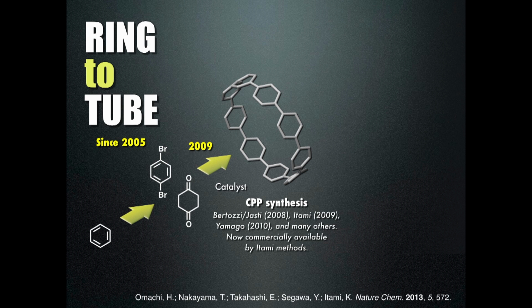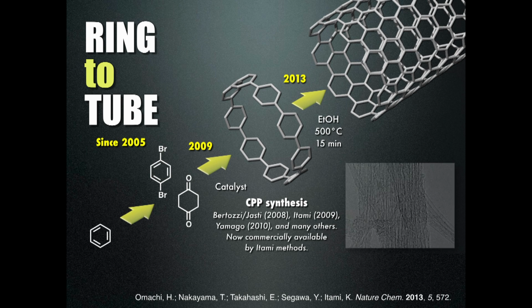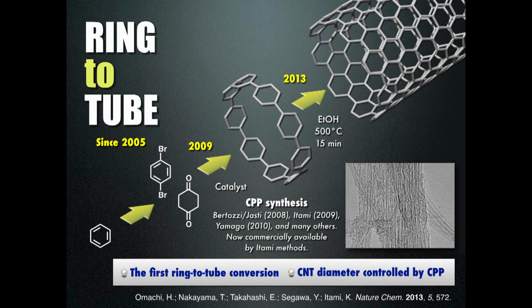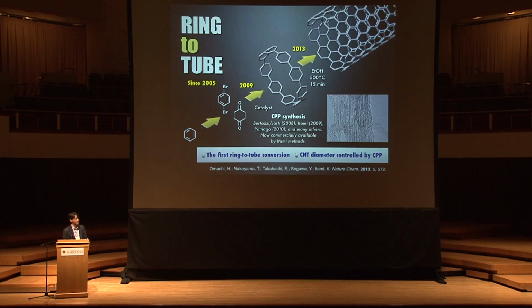It took another 4 years to accomplish making the tubes, but we were able to grow these rings to carbon nanotubes by treating this with ethanol at 500 degrees for 15 minutes. So this is the first ring-to-tube conversion. And the beauty of this strategy is that the diameter of the carbon nanotube can be controlled by the CPP template. But this is only a proof of principle study. We're not completely satisfied about this because the yield is low and the chirality control is not perfect yet.